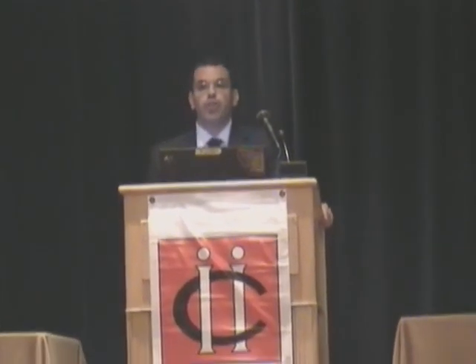One of the things that I didn't put in my presentation, it's also on the foundry standpoint, is unifying the temperatures we've been using. By doing so, we're not changing our temperatures of the preheat ovens anymore, and we're not touching the temperatures of the furnaces themselves, meaning that it's easier to degas and easier to maintain the melt on the daily routine.